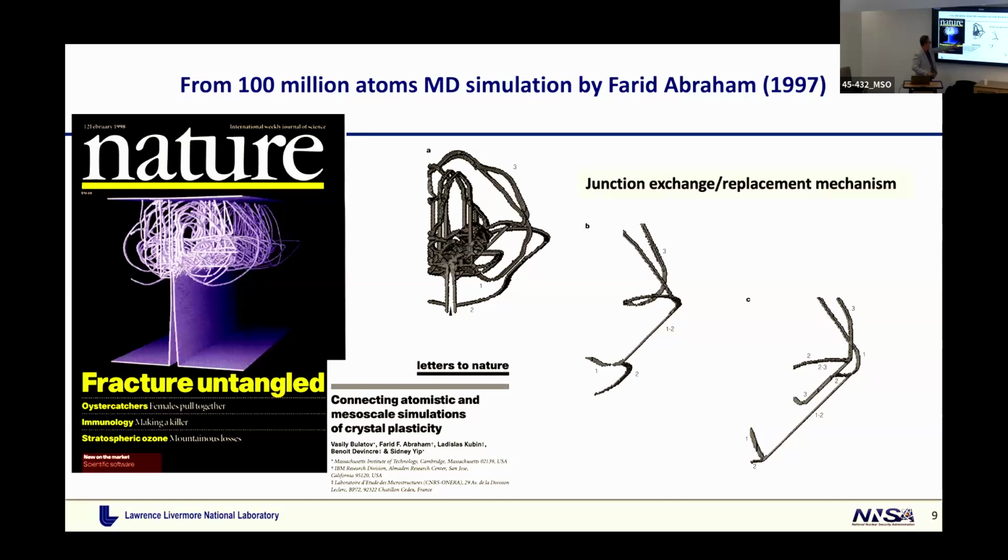One of them is shown here. You see that two dislocations, the same type but of different Burgers vectors, come close together. They like to join. They join into a junction, 1, 2. But then a dislocation number 3 is lurking behind somewhere, and it joins with 2 and begins to zip another junction, 2, 3. And by doing so, it unzips 1, 2. So it's a love triangle situation. It actually kicks out number 1 completely out of this partnership.